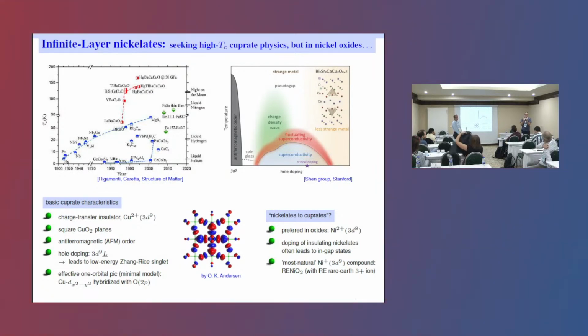In my view, the nickelates are a bit a coupling of two systems. So you have the in-plane system of nickel dx2-y2 and oxygen, which forms a strongly interacting entity. And then you have this nickel d3z2-r2 hopping to the rare earths, which are weakly correlated. So those two subsystems talk to each other in a very complicated manner, and this kind of two-subsystem entity we don't have in the cuprates. So that is my point of view.